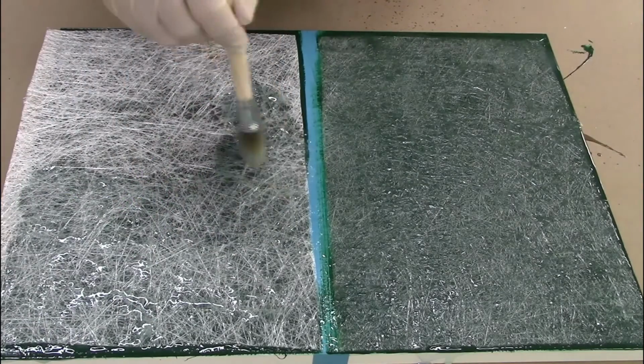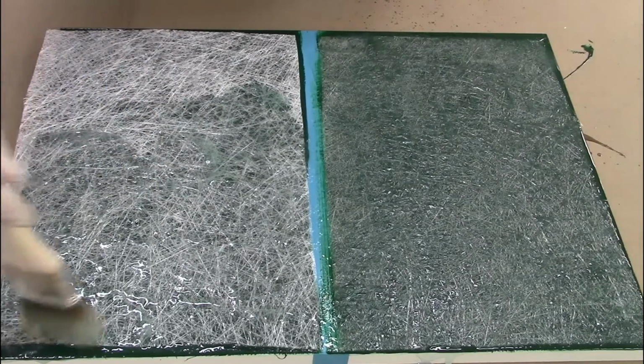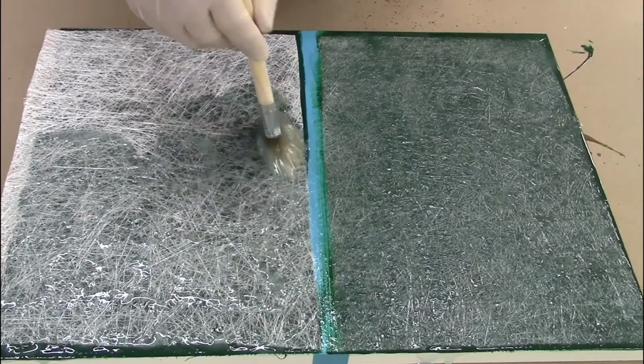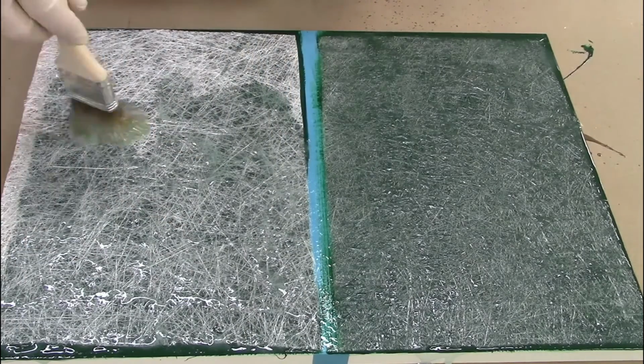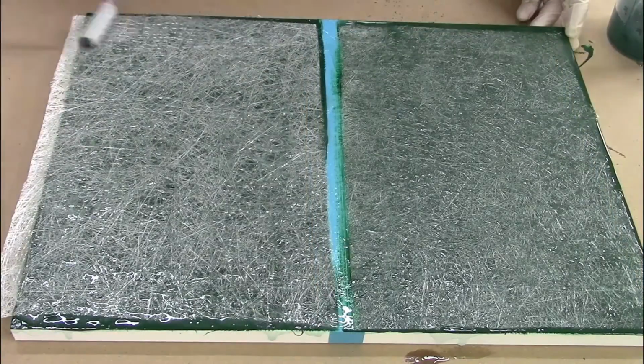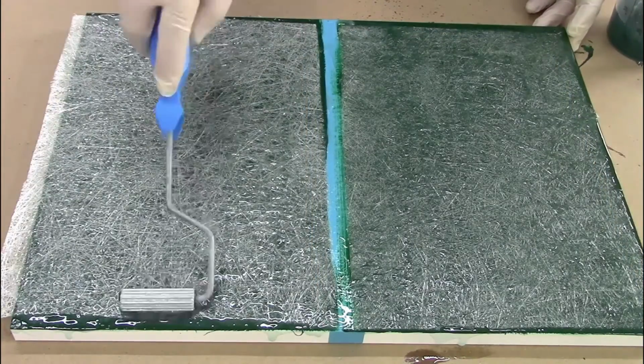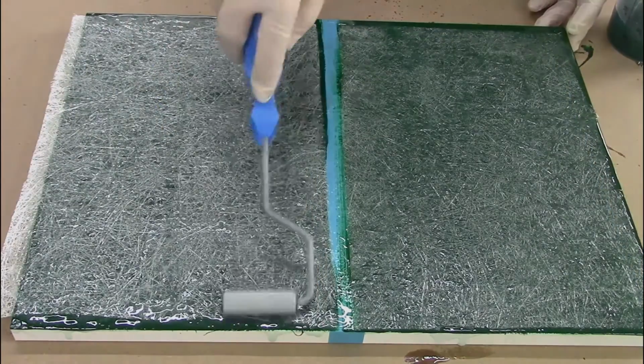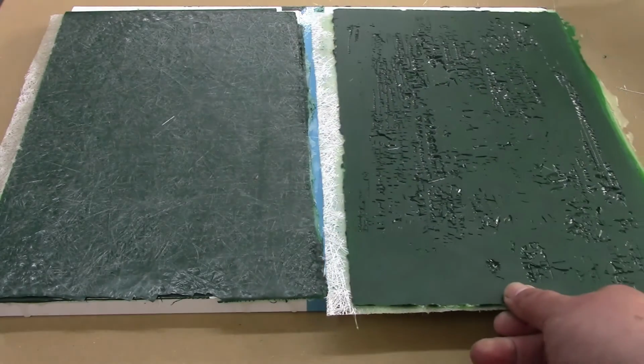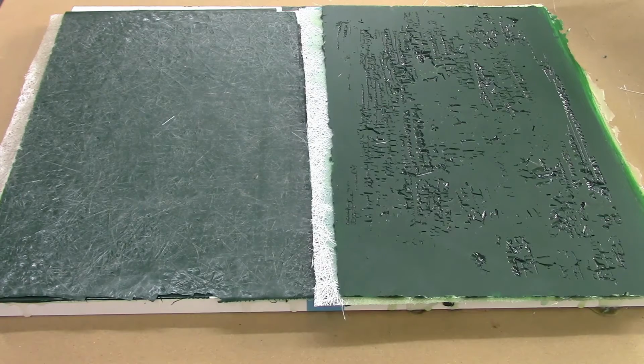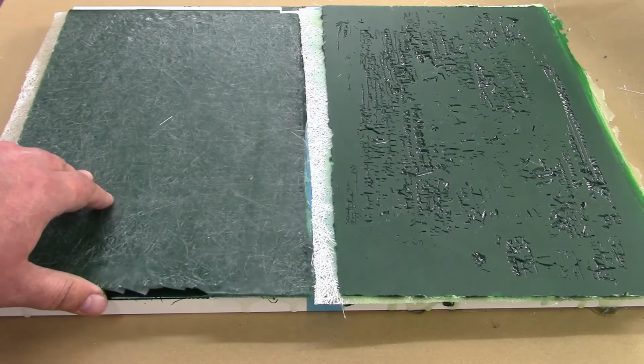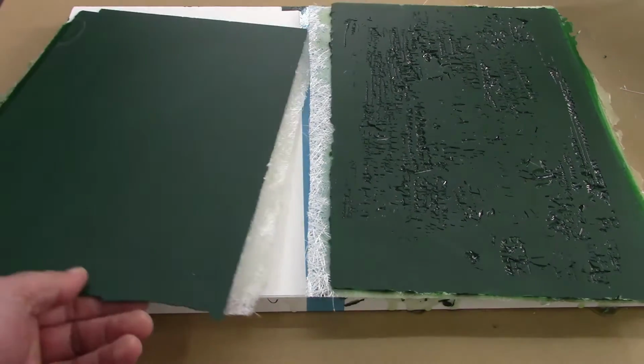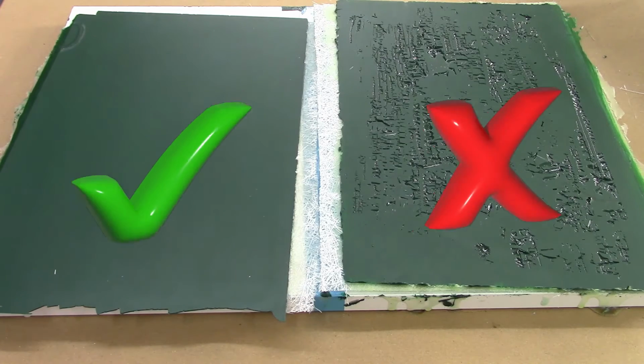It's also worth mentioning that catalyst should be thoroughly mixed into both your Gelcoat and resin. Poor catalyst dispersion can also cause some areas to cure slower than the rest of the laminate. As you can see, our cold, slow-curing resin has attacked our Gelcoat as expected, whereas the sample that cured within reasonable temperatures and at a much quicker rate has come out perfect.